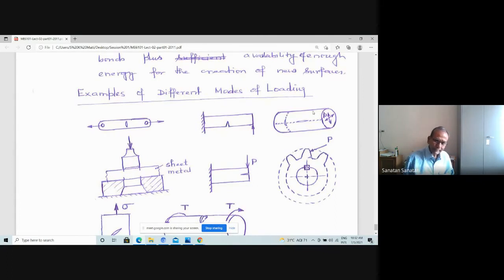In the case of a beam, look at that. The second example on the right, if you have a beam and a crack like that, you see that if you draw the shear force and bending moment diagram, at the crack location there is both bending and shear. So that bending is trying to open up the crack faces, so that gives rise to mode 1. And then that shear force which acts in that cross section, if you draw the shear force diagram, shear force is constant all along the length, and therefore if you separate the two parts of the component at the crack plane, the right one is going up and the left one is fixed, so therefore it is mode 2. Crack faces are moving parallel. So that is a mode 2 example.